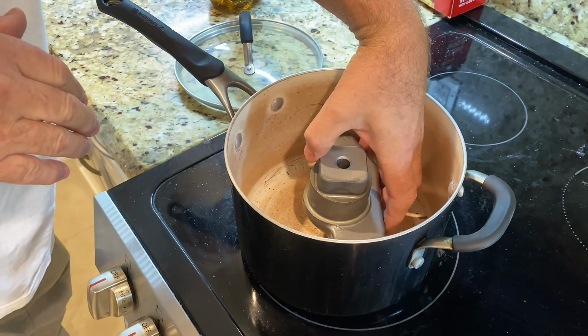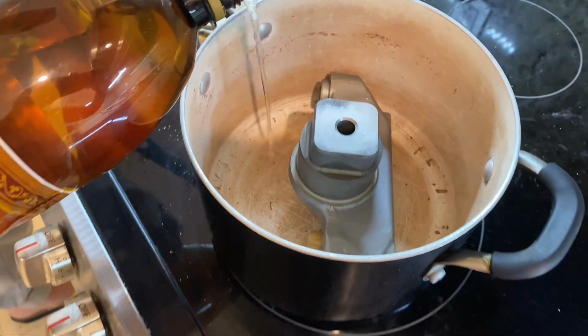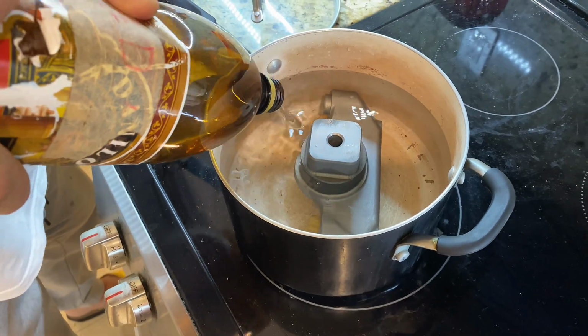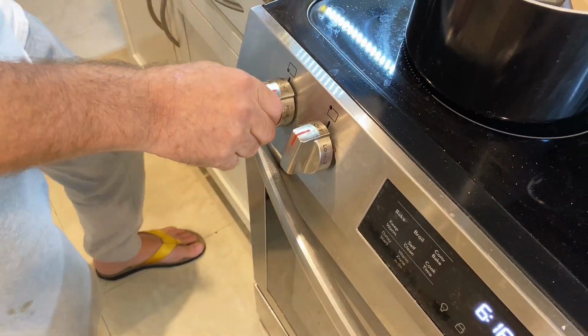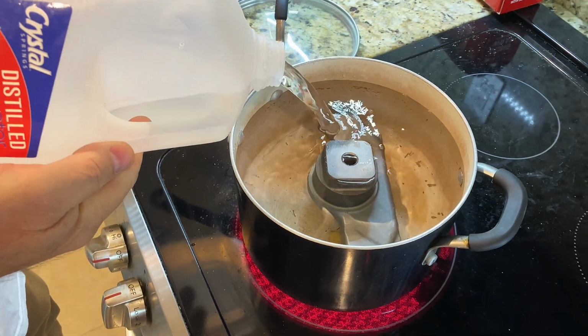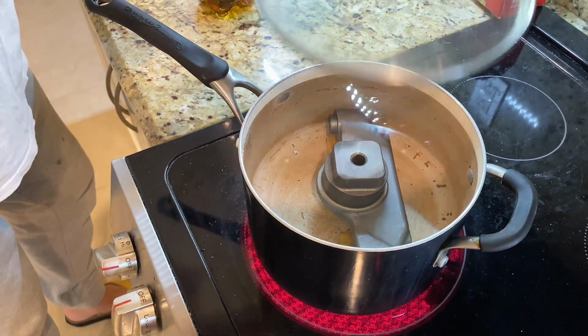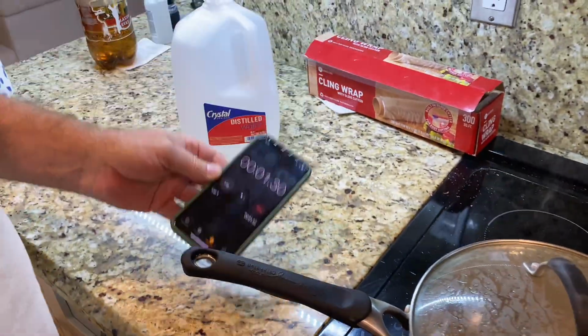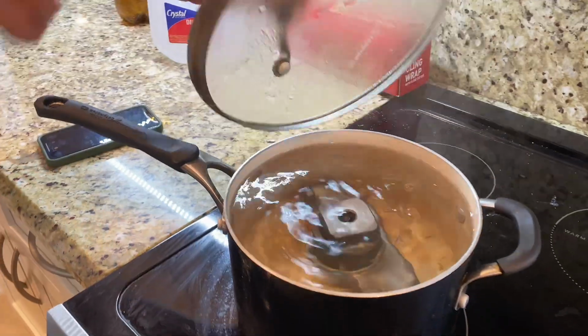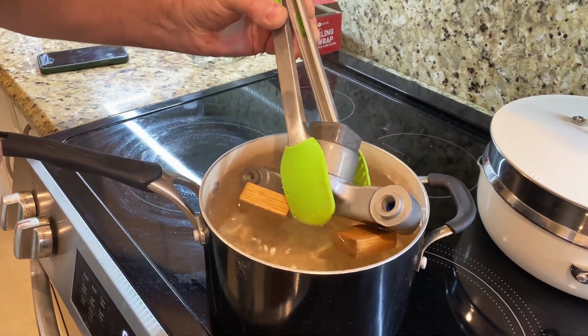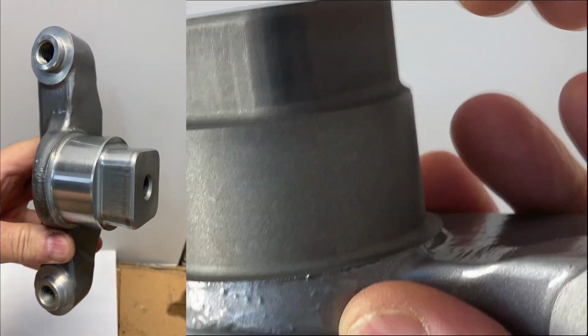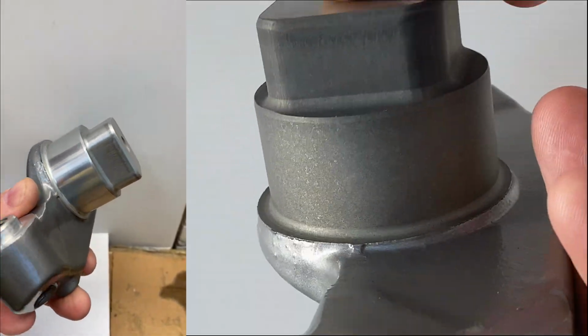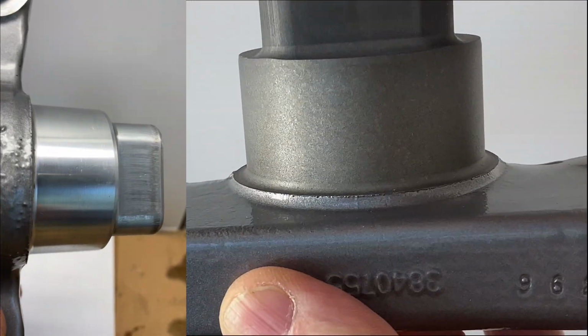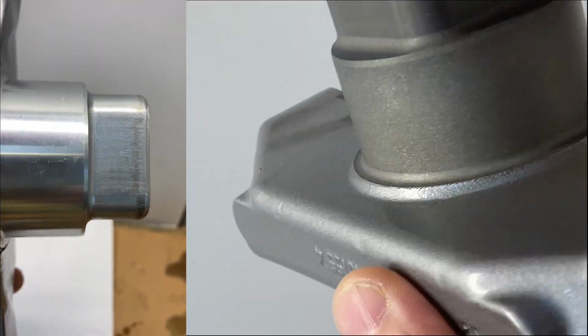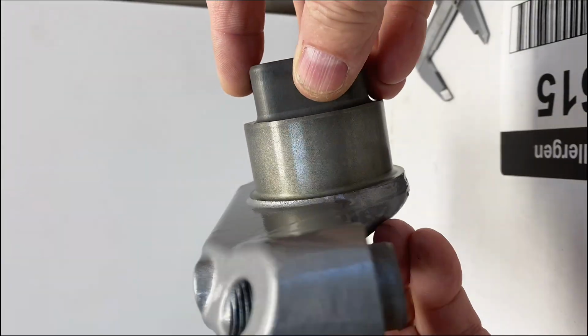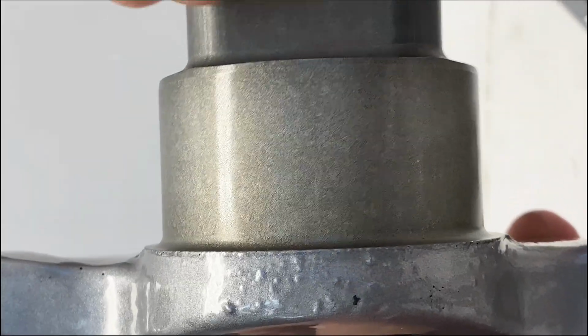But that isn't all. The shaft must also be boiled, so that the pores on the surface of this layer close up, and the coating becomes even more durable. I boil it in distilled water for 15 minutes in a pot that my wife allowed me to use. This is the before and after result. I polished the area for the bushing. The coating is much harder than aluminum and polishes very well.